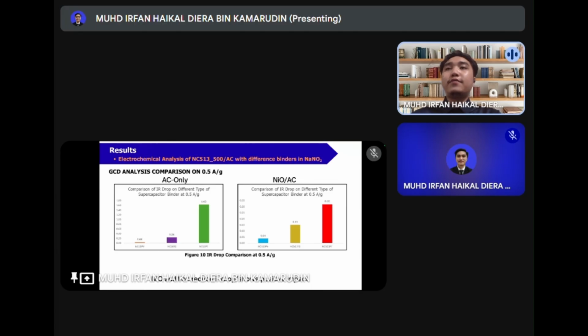Next, this slide shows the galvanostatic charge-discharge (GCD) curves at 0.5 A/g, highlighting the internal resistance (IR) drop for different binders. The key points are PVDF shows the lowest IR drop, confirming its strong conductivity and interfacial stability. Adding NiO reduces the IR drop for all binders, improving overall charge transport. For Tapioca Starch (TS), capacitance slightly dropped with NiO as seen in CV.